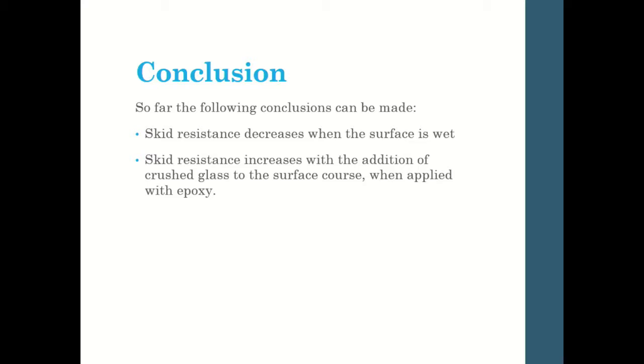Instead of using epoxy, I am looking into the option of tamping, where I'd apply force to the surface of the asphalt sample while it's hot, so that would eliminate the need for epoxy. So that is also being explored, and I'm also exploring using different size fractions of glass to see what size would be more optimal for this study. That brings me to the end of my research.